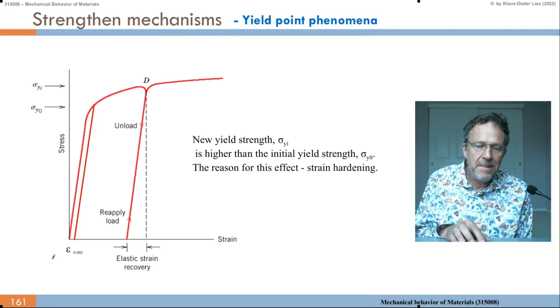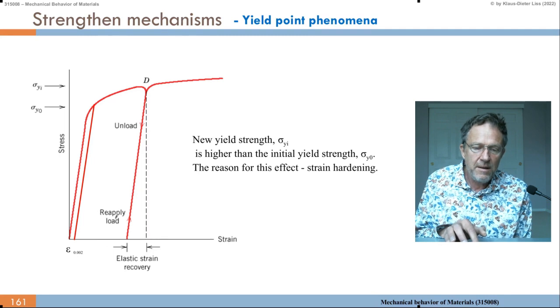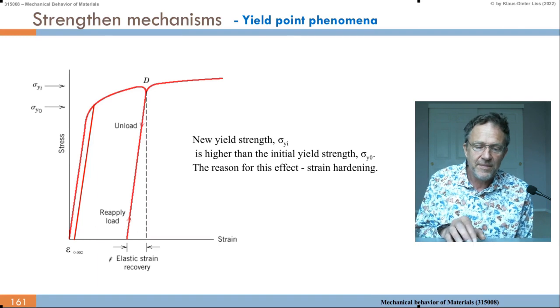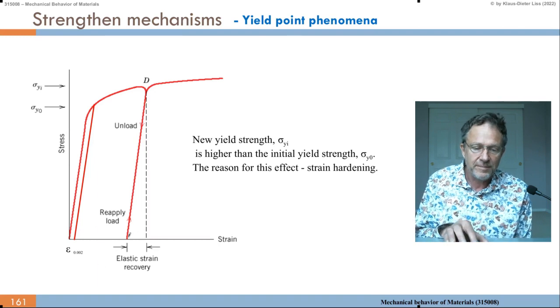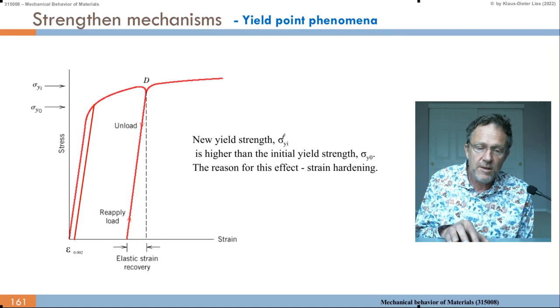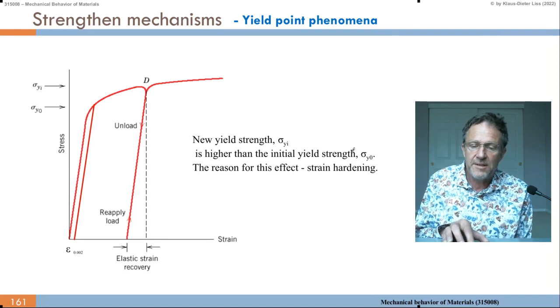That means it depends whether I take a workpiece which has been annealed, then we get sigma 0, or which has already been work hardened, like the rolled or wrought material. Then I get a higher yield point than sigma yield 0. So the new yield strength, sigma yi, is higher than the initial yield strength, sigma 0. And the reason for this effect is strain hardening.